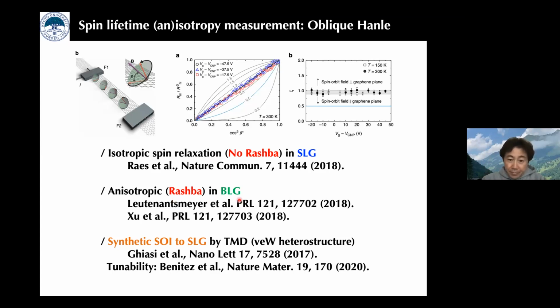But experimentally, in bilayer graphene, spin lifetime is anisotropic. This means a Rashba field exists. Currently, nobody precisely understands the physics of why single layer graphene does not have a Rashba field, and why bilayer graphene can induce a Rashba field, although only one graphene layer is additionally stacked on the single layer graphene.